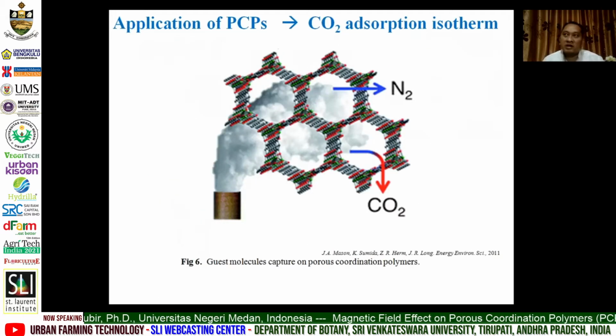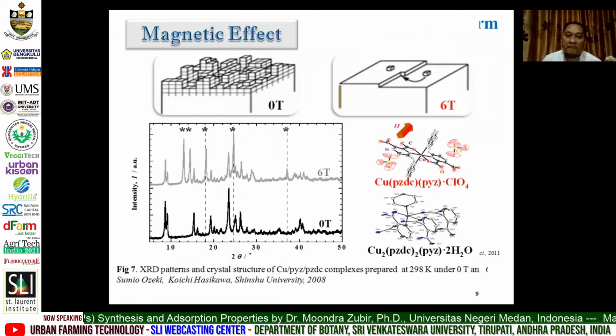Besides catalysts or biosensors, I use PCP for gas storage application. In this experiment, we observe the pore properties by nitrogen adsorption, and then carbon dioxide adsorption, and how the magnetic field affects the synthesis and also the adsorption properties. If we synthesize the PCPs at 0 Tesla, or no magnetic field, the crystals grow disordered. Besides that, if we prepare them in a magnetic field, the crystals grow slowly and form an ordered crystal structure.